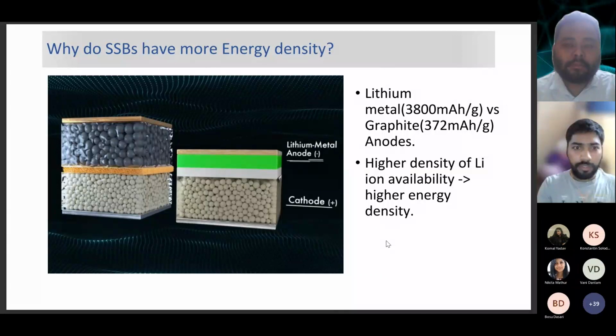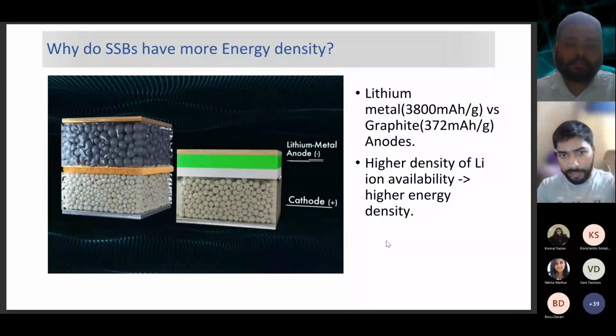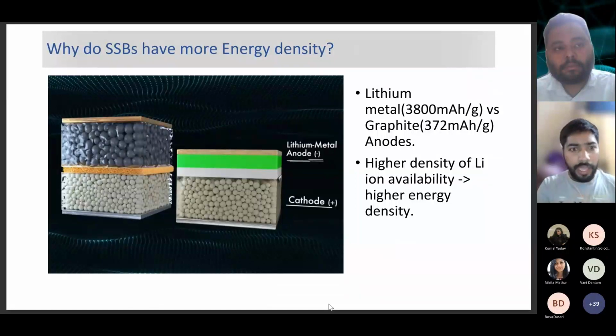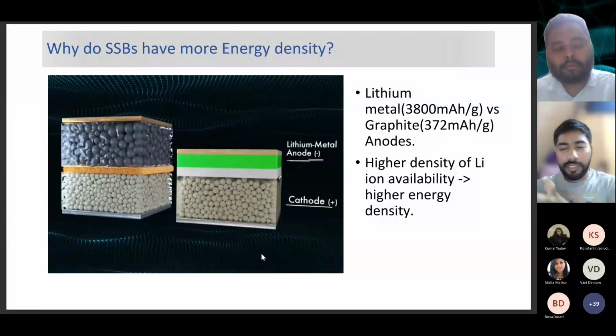Of course, in the case of the cathode, there is no change because both of them use the same cathode material. That again depends on whether you are trying to develop a new cathode, but that's a different thing. As of now, from the anode's perspective, we are able to use a lithium metal anode, and this is the reason I mentioned the dendrite challenge in the first slide, because we could possibly have used a lithium metal anode for the conventional cell as well. In fact, when I'm developing and testing cells in the lab, I use lithium metal for conventional cells as well. But the problem is the liquid electrolyte and the separator. It's not strong enough to suppress the dendrites after a few cycles. Once I charge and discharge the cell for n number of cycles, it's going to start forming dendrites and have an internal short circuit. But with the solid electrolyte, there is a possibility that they may be able to suppress the dendrite formation at a higher level than the conventional cells. Next slide.